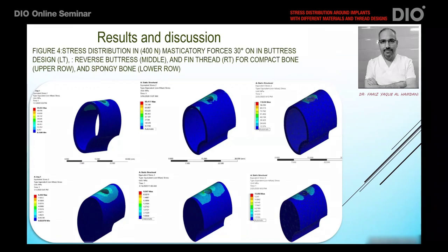this will not only prevent any damaging effect on the bone, but in fact it might have a promotive, useful effect on the bone in terms of bone production, because you are stimulating the bone. Physiological stress, when it is within the limit, might stimulate bone formation. Contrarily, if you have more occlusal load than the physiological limit of the bone, you will end up with bone loss and failure of the dental implant. In these three conditions, the stress is within the physiological limit, so this might in turn stimulate bone formation.